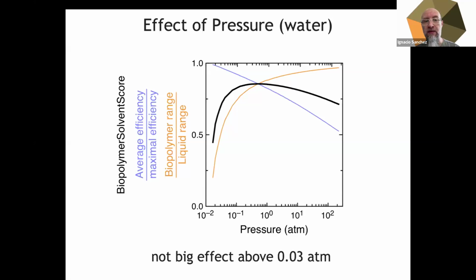And we find that even though the components of the score, the purple and orange lines, do vary significantly within this range, the effect of pressure is not so strong above 0.03 atmospheres. So is there going to be an effect of pressure on our calculations? Yes, but not a very strong one.